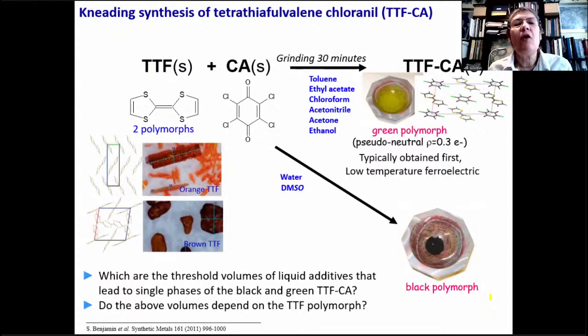So the synthesis of tetrathiafulvalene chloranil is shown in here, leading to this green phase, which is pseudo-neutral. So 3 in 10 molecules are ionized and the other 7 remain neutral. And the structure of this material has been known for many years, and it is a low temperature ferroelectric that undergoes a neutral, or pseudo-neutral, to pseudo-ionic phase transition at around 81 Kelvin. But the other polymorph, the black polymorph, has only been mentioned in the literature, and it has been less studied or less well characterized than the green form.